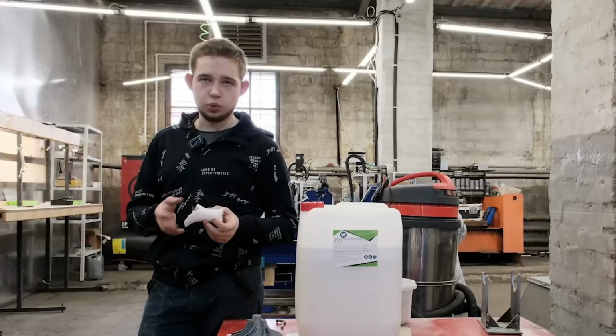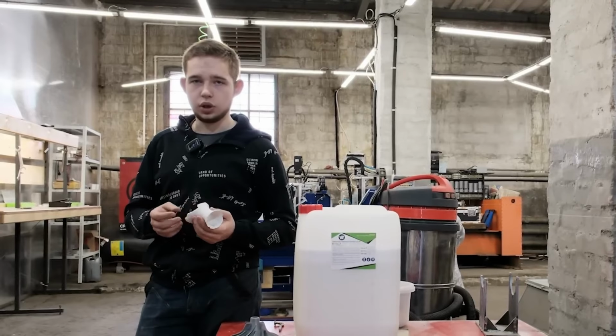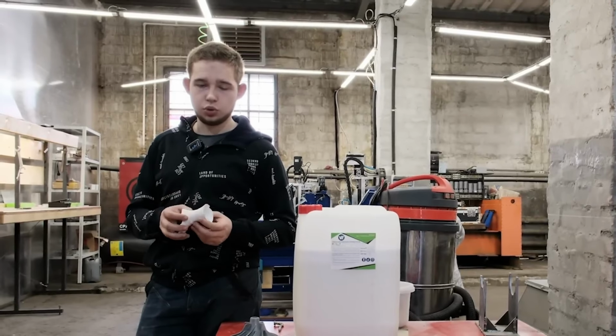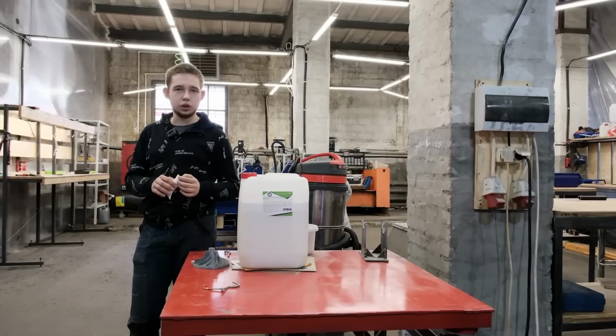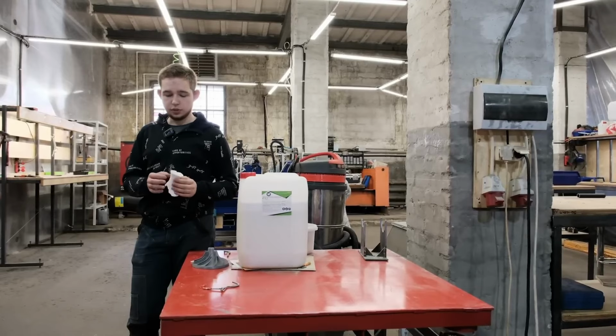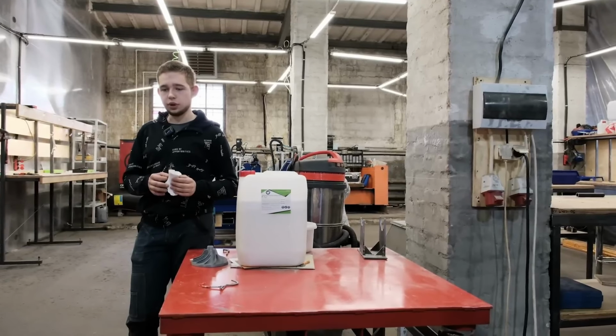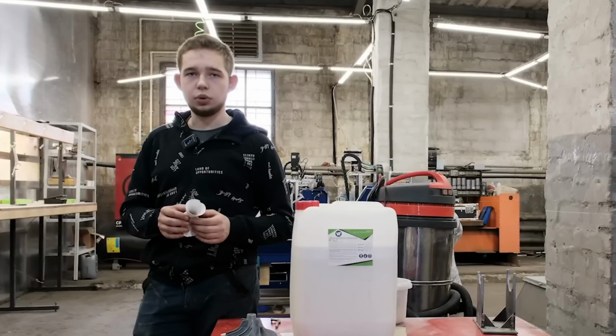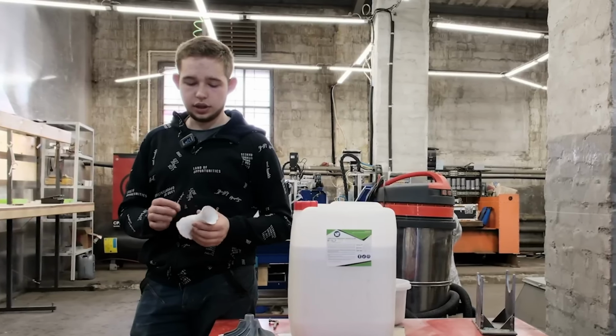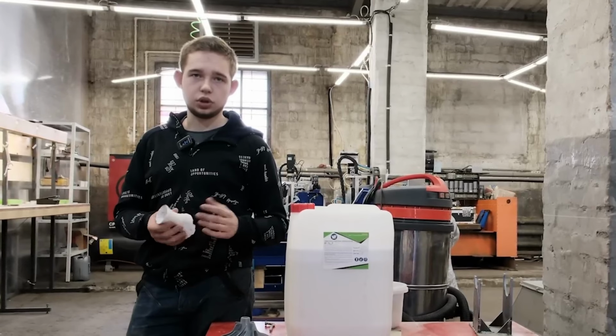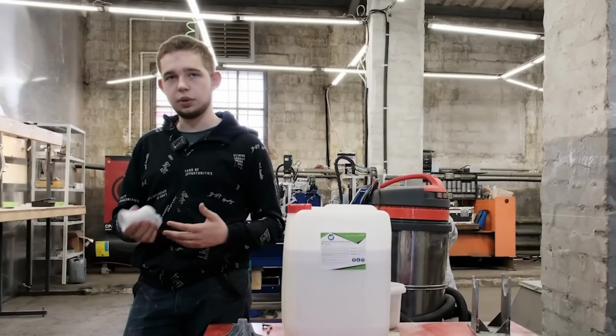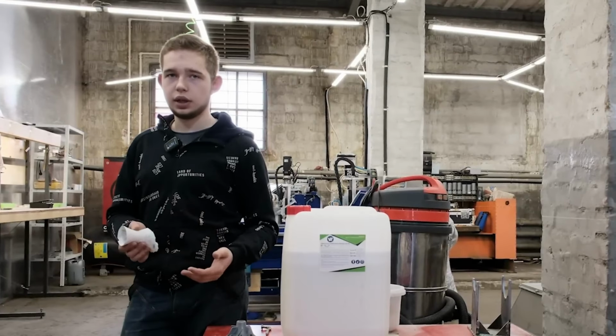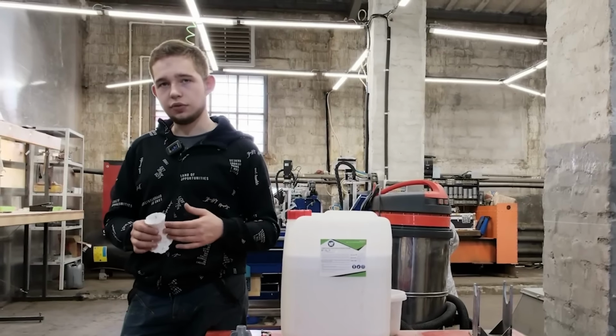Here, we specifically utilized electrocorundum as both the filler and the coating. Perhaps we didn't follow some part of the technological process. But this ceramic turns out to be very unstable when exposed to temperature fluctuations. That is, even if it is, say, heated up to 600 degrees, but while it is being taken out of the muffle furnace, it cools down a little, and then aluminum is poured in, the temperature difference causes it to crack immediately.